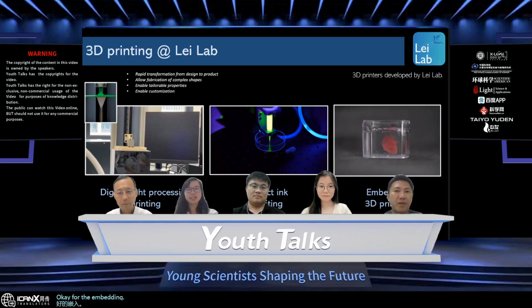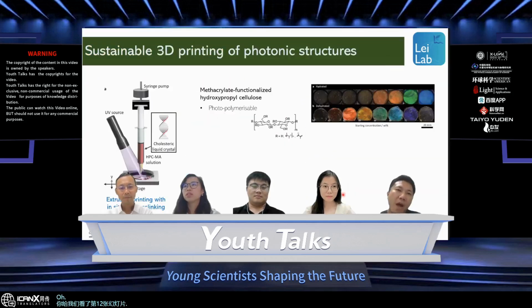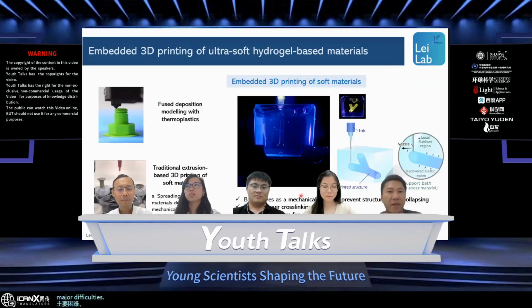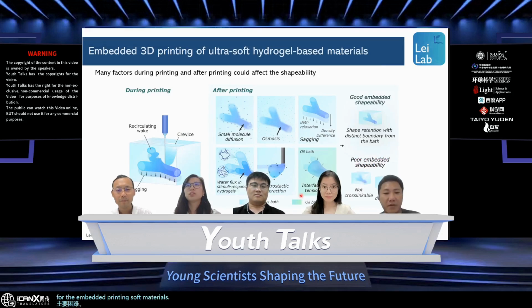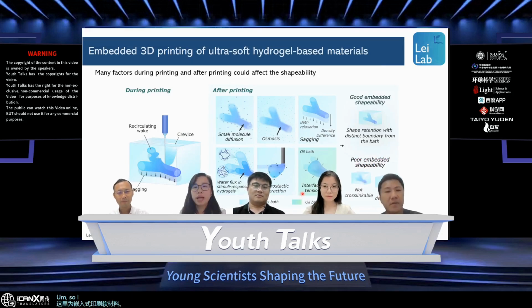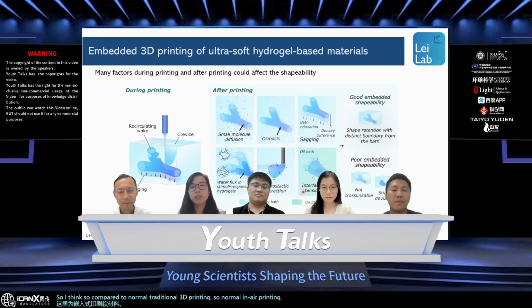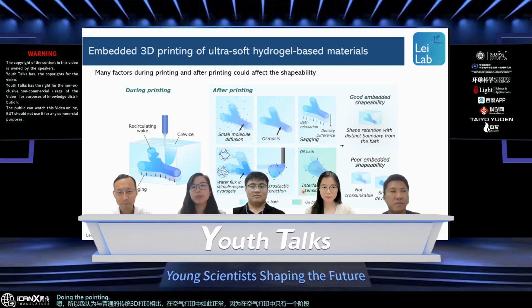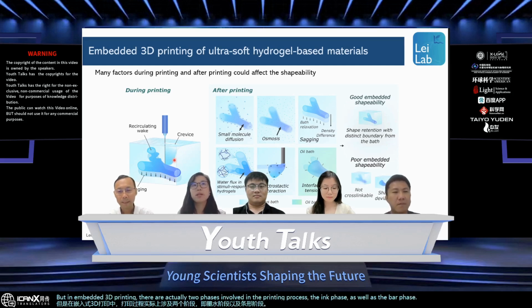Okay, for the embedded printing of soft materials you show us on slide 12, what are the major difficulties? Compared to normal in-air printing, where there is only one phase involved during printing, in embedded 3D printing there are actually two phases involved, the ink phase as well as the bath phase. So we need to match the properties between the ink and the bath.